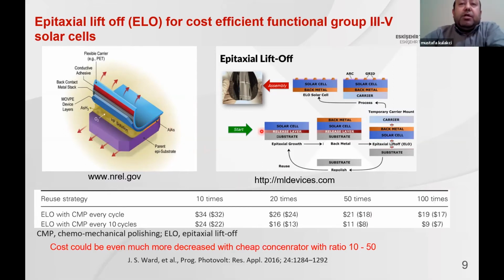Here you see the general approach. Of course, there are some steps not included here. Only main steps are included. Of course, the device fabrication using epitaxial liftoff is very difficult compared to the conventional case. First, you have to extract this active layer without any deterioration in the film structure, which is a single crystal over the substrate, without any crack or any loss. Then you should transfer without any loss to the new carrier.